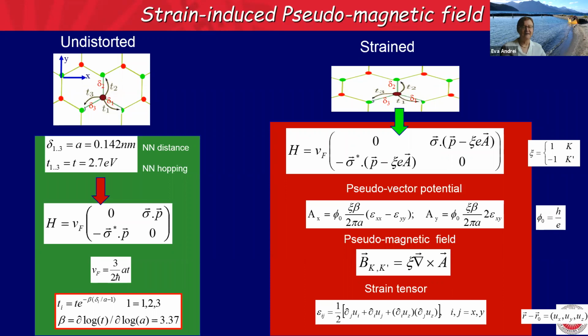the ratio between the stretched bond and the original bond, and this is this exponential expression here. Beta here is the Gruneisen parameter, and then you get a Hamiltonian where VF actually depends on position, and we all know that when that happens, you can apply first order perturbation theory, and what you get is an emergent gauge field, which I called A here, which is like a vector potential. Notice the xi here has opposite signs in the two valleys, and this is very important. So A is basically a vector potential, which gives you a pseudo-magnetic field.